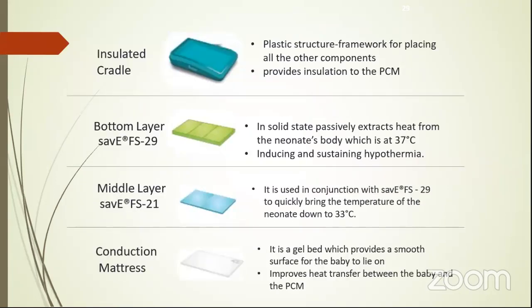So these are the 4 layers we have. At the bottom we have the insulated cradle to hold all these layers. This is a plastic structure framework for placing all the other components and provides insulation to the PCM. Insulation means we insulate the outer surface of the PC materials. And the bottom layer, in solid state, passively extracts heat from the neonate's body, which is at 37 degrees Celsius, inducing and sustaining hypothermia, right?